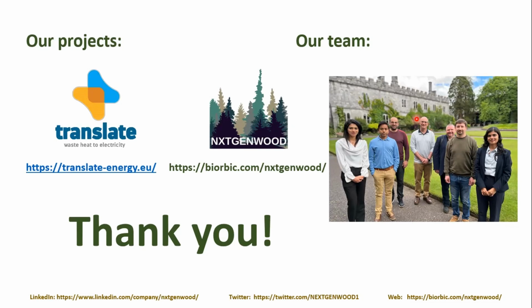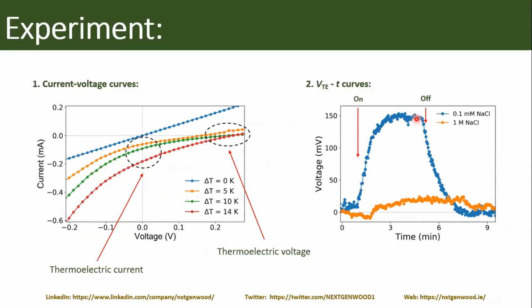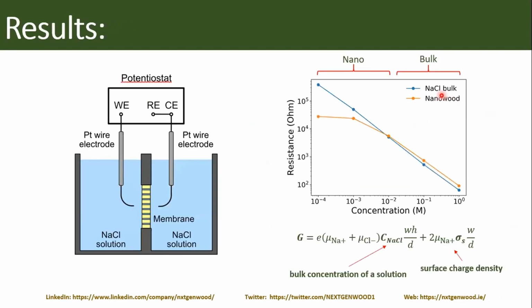And then since they are round, you just have these channels in the space between them, but you don't really have microchannels or something big. And we can easily control it using electrochemical impedance spectroscopy. So you can definitely define the case where you have these large channels and then the whole structure behaves like bulk electrolyte. And then, for example, if you go back to this picture, you will always get just typical behavior for bulk electrolyte. Maybe the resistance will be higher or lower, but the same trend.